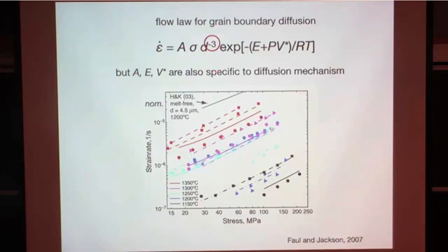So we can determine these parameters, where I have to say these experiments are all done at 300 megapascal gas pressure. So we don't determine the activation volume. 300 megapascal is about 10 kilometers depth; in terms of the mantle, that is not very much.